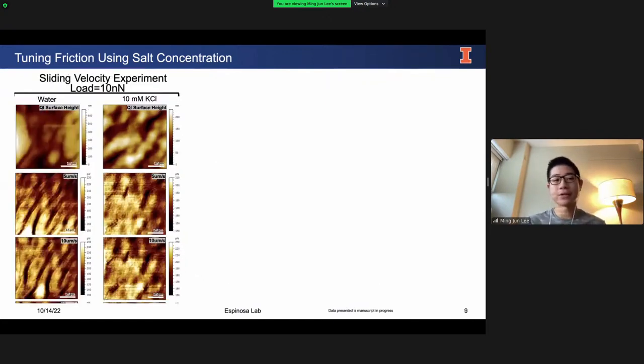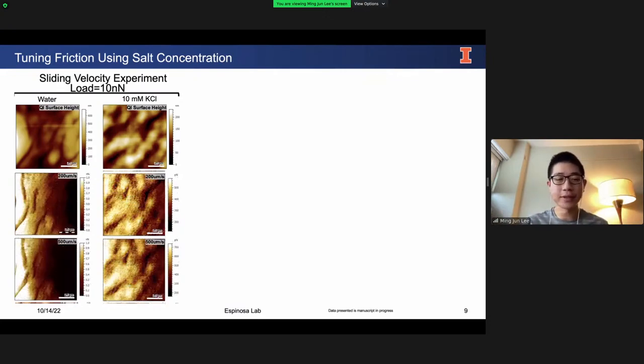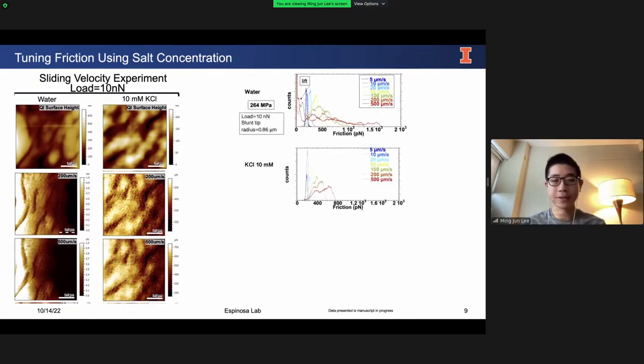Next experiment I'd like to show, I have reversed the parameters this time into the sliding velocity experiment. So now I fix the applied load to 10 nanonewtons, but I change the sliding velocity of the AFM tip, starting as slow as 5 microns per second, increasing to 10 microns per second. There are some intermediate speeds, and then finally ending off with 200 microns and 500 microns per second. Once again, the same positioning of the histogram values I've summarized here.